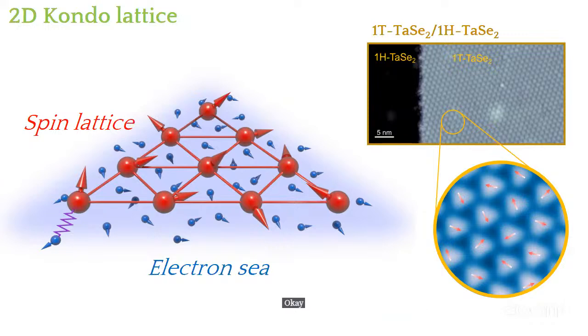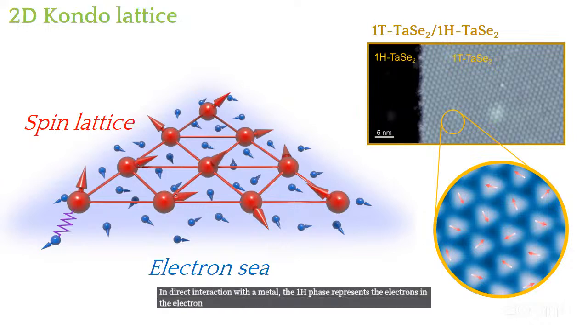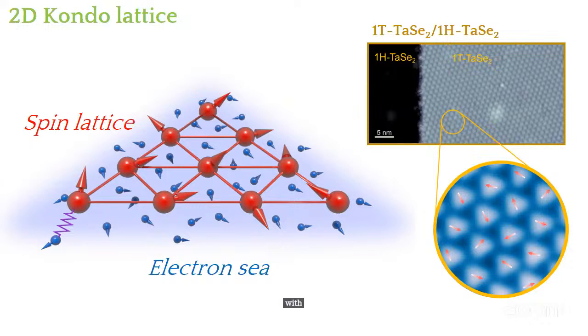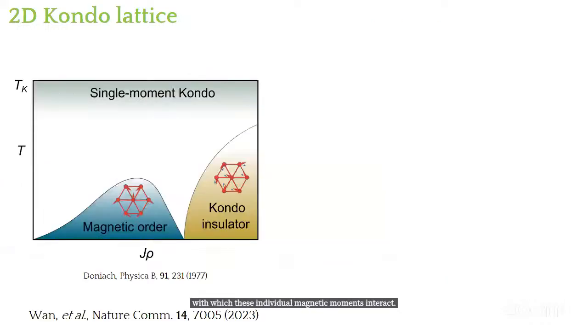Okay, so you can see this as a two-dimensional Kondo lattice where the 1T layer hosts the spin lattice, in direct interaction with the metal. The 1H phase represents the electron pool of conduction electrons with which these individual magnetic moments interact. Okay. So what we did, we studied the ground state of this collective phase. If you look at the literature in the past, you immediately find the Doniach phase diagram, which is simplified, but looks like this.